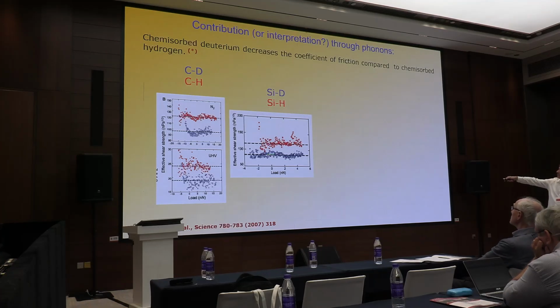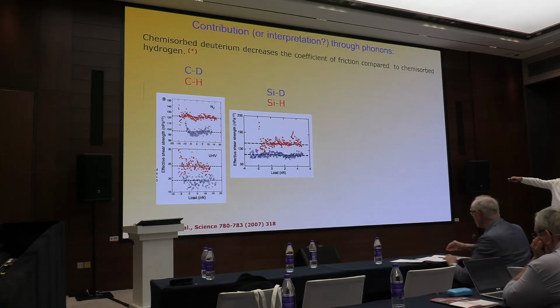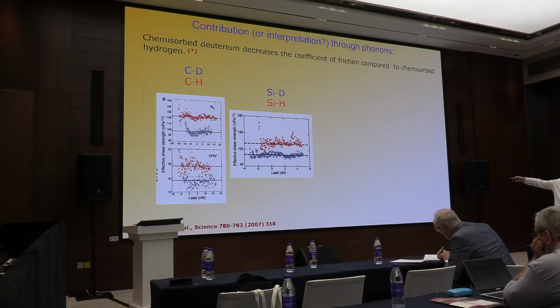This is silicon with deuterium and silicon with hydrogen. The blue is deuterium. The red is hydrogen. Here is in ultra vacuum, and here is with atmospheric nitrogen, pure nitrogen. In all cases, you can see that the effective shear stress, that is the resistance to the motion of the tip on the surface, is lower for the material with deuterium.